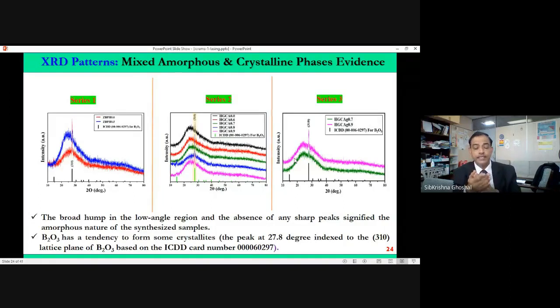How do we know? Another proof that this material is glass and crystallite together. That means in the background of the glass, majority is glass, but there are little crystallites in the material. So we have seen that there are sharp peaks in the X-ray diffraction. We'll also do Raman. We'll also do XPS to prove further, because only one investigation will not be enough. You have to cross-correlate. You have to bring other evidences, cross-evidences, to re-verify, reaffirm that this is really true. So these are basically the X-ray data.